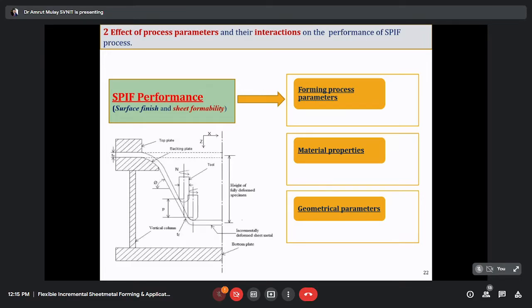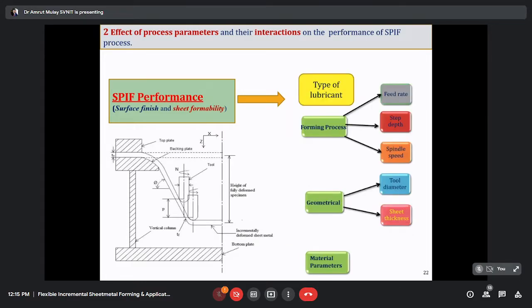Now you can see these are the parameters and forming processes which are controlled in the CNC machine: feed rate, step depth, spindle speed, tool diameter, and sheet thickness. The forming parameters, that is feed rate, step depth and spindle speed, are in the hand of the operator and can be controlled on the CNC unit. And here are the geometrical parameters, which we can control manually. For example, the tool diameter, 8 mm or 10 mm, you can select on your own, and sheet thickness you can use.